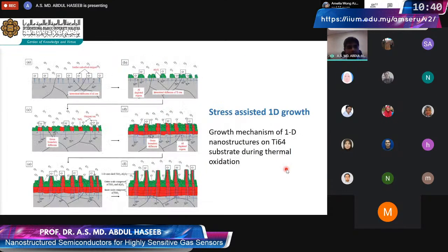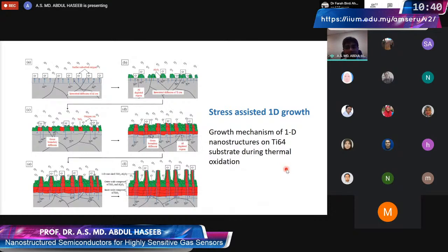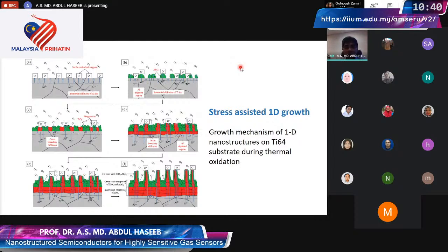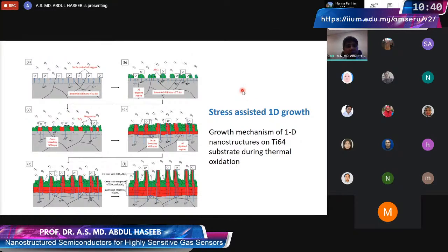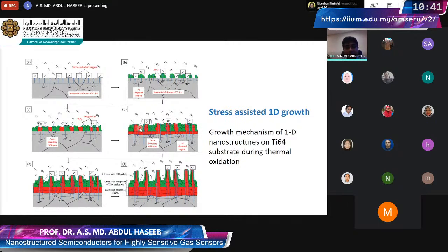And we proposed a mechanism for how this grows. In fact, it was not our discovery. We found in the literature people explaining things in different systems, and from there, we borrowed some ideas. And here we propose that what happens is a stress-assisted one-dimensional growth. And initially, aluminum tends to segregate to the surface. And we know this from the high temperature corrosion literature. People have found that out earlier, that aluminum tends to segregate there. And once aluminum segregates to the surface, it forms oxides at different places. And titanium then also tends to diffuse along the grain boundaries, and then they move up. And when they are moving up and are exposed to oxygen, they also become oxidized. So we now have at the outer layer a mixture of oxides of titanium and oxides of aluminum.